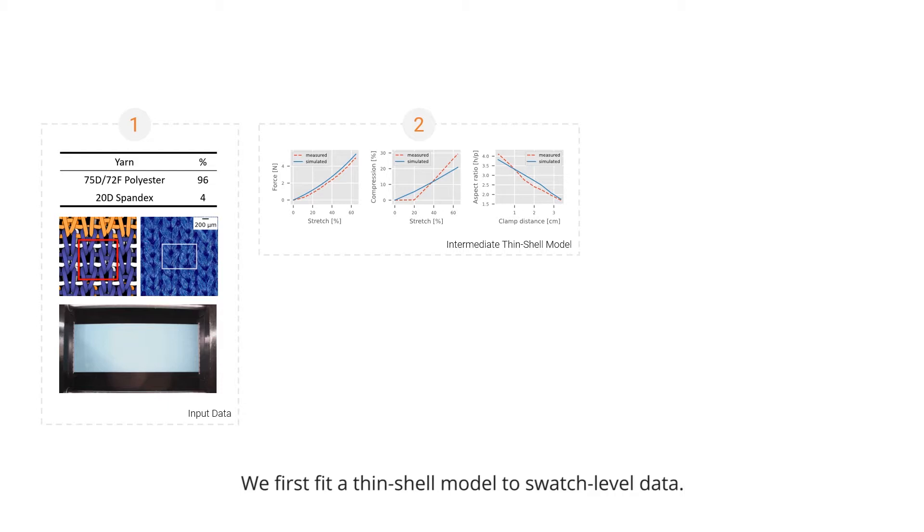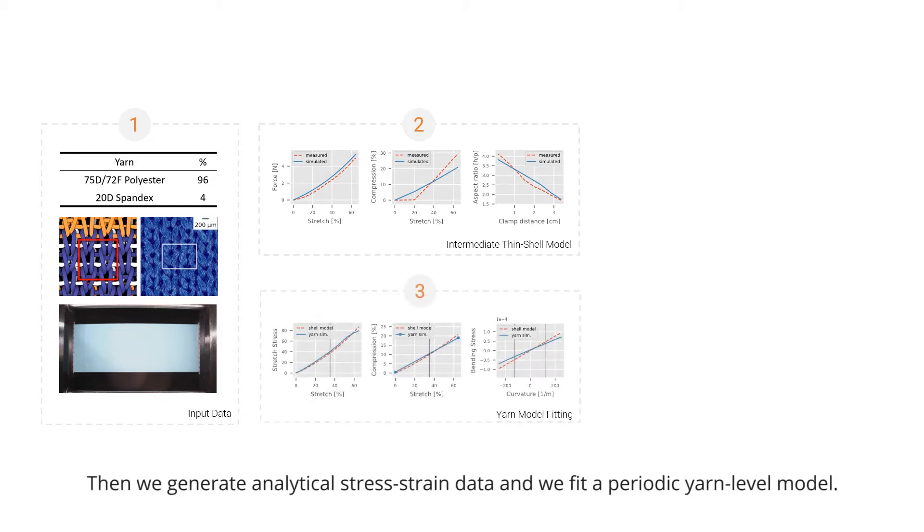We first fit a thin-shell model to swatch-level data. Then we generate analytical stress-strain data and we fit a periodic yarn-level model.